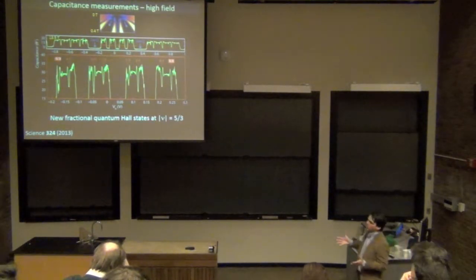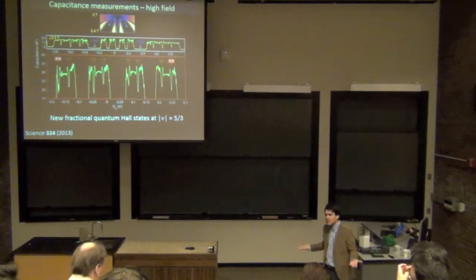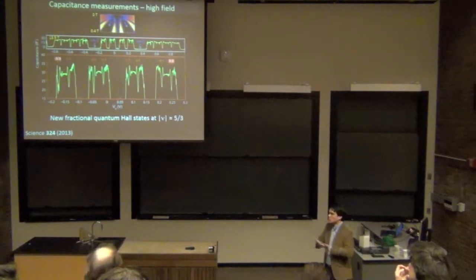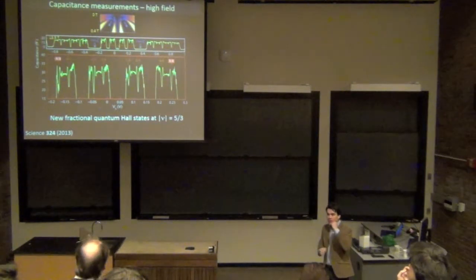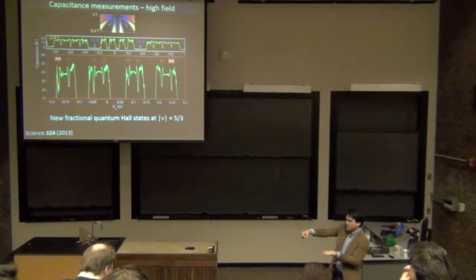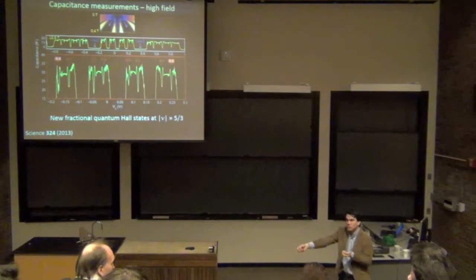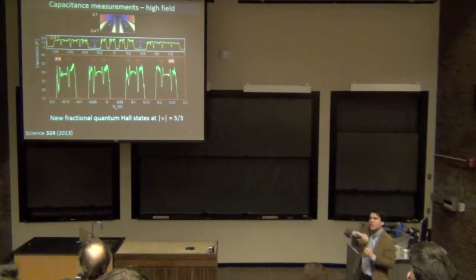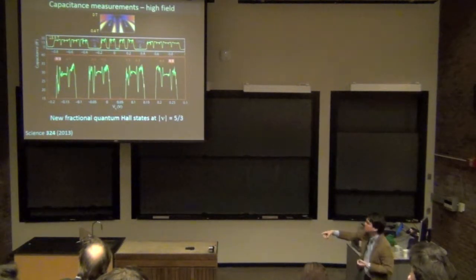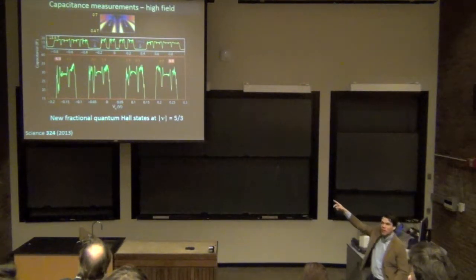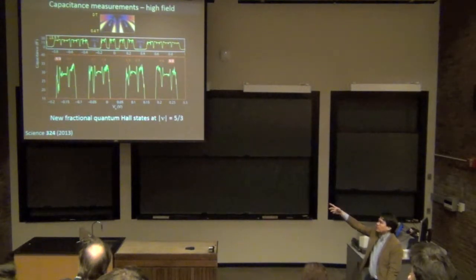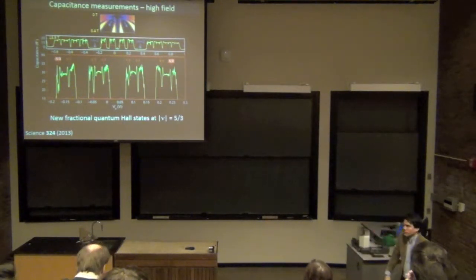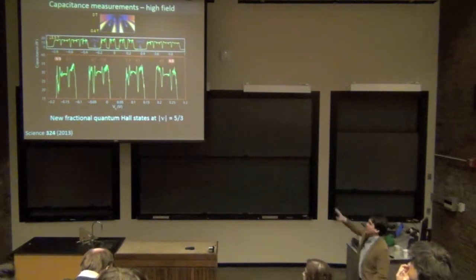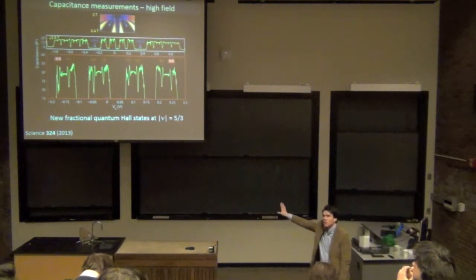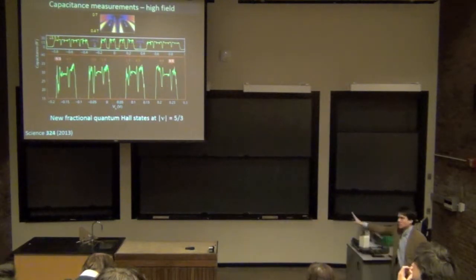So the fact that we observe them in our system and they don't observe them in the massless system seems to be an indication that what we're seeing is AB sublattice symmetry breaking. Because the excitations involve hopping from one sublattice to another, as soon as we break that symmetry, it becomes much more expensive to hop electrons from the A sublattice to the B sublattice. And so the gaps that we see end up being much larger, and that points to why we're actually observing them. So this is another piece of evidence that we're seeing AB sublattice symmetry breaking in our system.